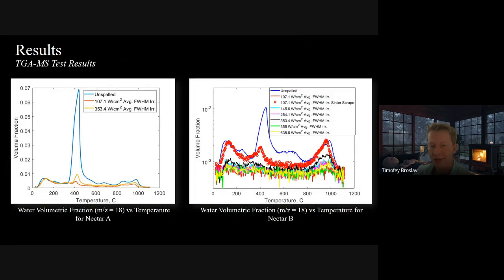This also showcases the actual water pressure fraction, in this case water volume fraction, which you can basically treat as meaning the same thing, showing that unspalled samples of Nectar A and Nectar B did have a significant water fraction in the 400-degree range, while spalled samples did not, showing that they did lose the majority of their water, both Nectar A and Nectar B samples.